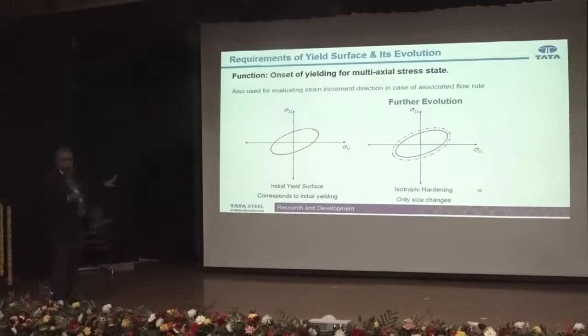And one of the easiest simplifications is isotropic hardening. What is isotropic hardening? You just say that irrespective of what deformation path I assume, the yield surface is going to increase by an equal amount in all directions. This means if I give a simple tensile deformation in this direction, it has increased from here to here because of the strain hardening, but it has also increased in the reverse direction. So if I deform a small amount in tension and then do compression, it will actually tell me the same yield stress, right?